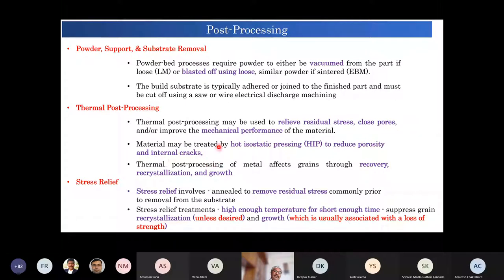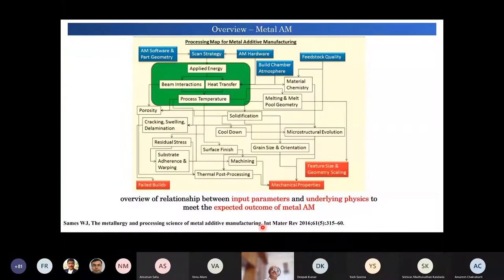Also, the internal cracks can be minimized if they are below a critical size. But of course, it is not so effective in minimizing the cracks. Some porosities can be taken care of. And then, of course, as I said, microstructural control like recovery, recrystallization, and grain growth is important. Stress relief annealing is required because residual stresses have to be removed. And then one can do it at higher temperature and for short enough time so that there is no appreciable microstructural change during those treatments.